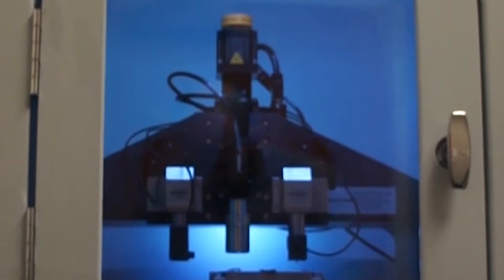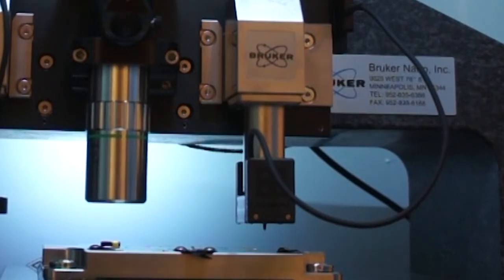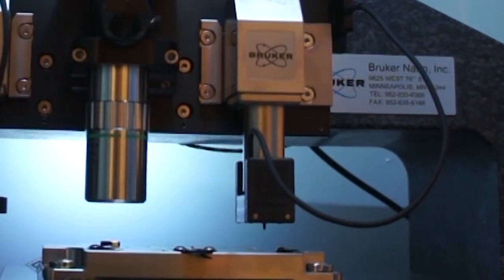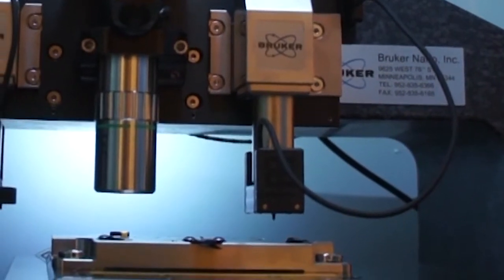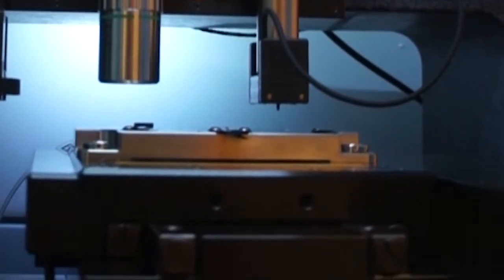This is our Hysitron TI-980 triboindenter, often simply referred to as our nanoindenter. Nanoindentation involves forcing a rigid probe into a sample to determine that sample's mechanical properties, primarily reduced modulus and hardness. The maximum displacement of the indenter tip is about 5 microns, and thus the testing volume is usually no more than a few thousand nanometers, making it extremely sensitive to the outermost surface of a sample or material.